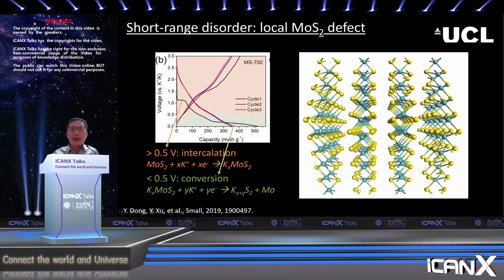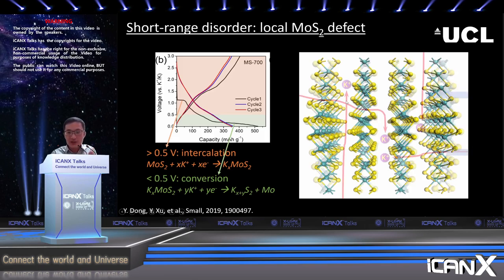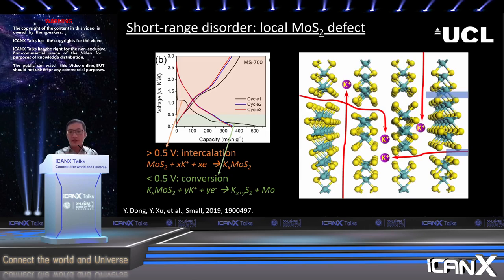So what we think is if we can open up each layer, we can give extra tunnels where the ions can actually diffuse through the layer into the interlayer space. Then we can increase the intercalation sites. We can increase the surface area of the material. Both would contribute to the increase of the capacity of the material. So by using these so-called local molybdenum sulfide defects, we're able to take out some molybdenum sulfide molecules and make defects in each layer so that we can transform this 2D diffusion of ions into a 3D diffusion manner.